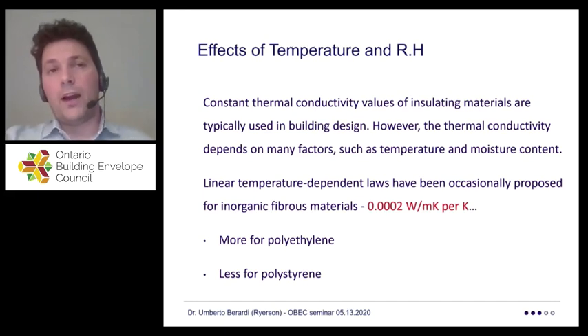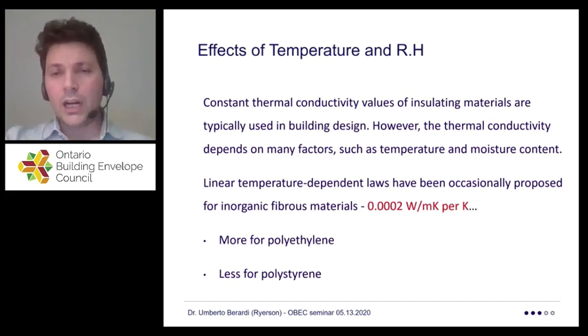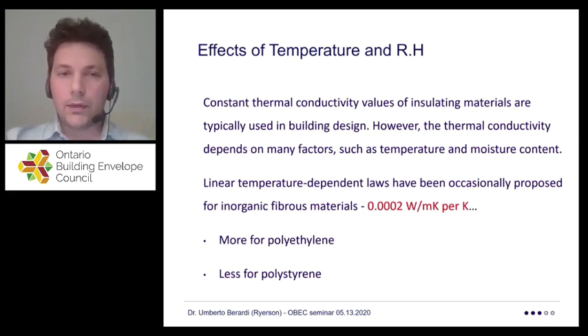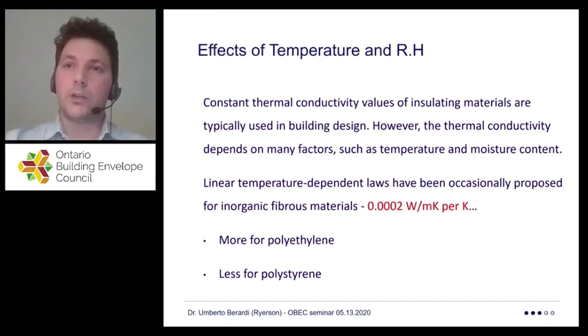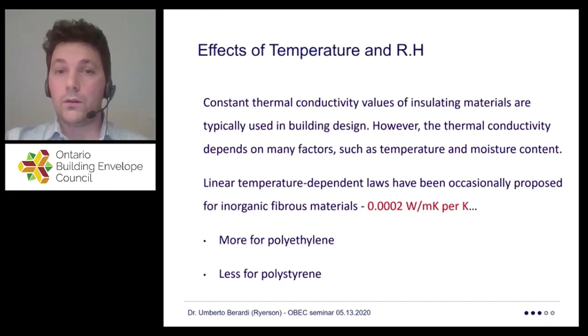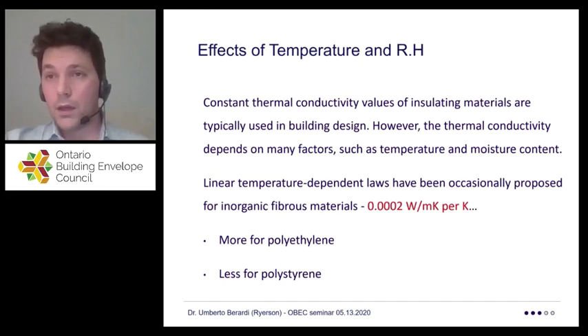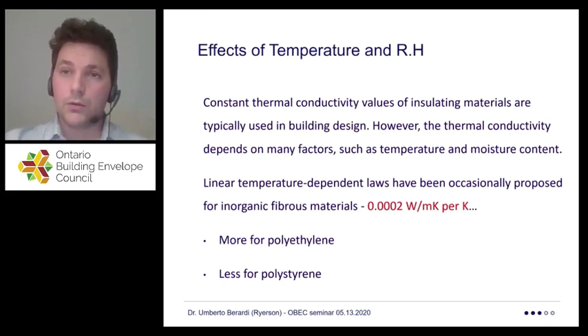So first of all, temperature effects on thermal conductivity. In general, although we typically use constant thermal conductivity, I'm safe to tell you today that every material will have at least a linear temperature-dependent law. The linear temperature-dependent law really is an effect of radiation. Higher temperature brings more radiation, which brings more thermal conductivity. So typically, a safe assumption could be to use a dependency in the range of 0.0002 watts per meter Kelvin per Kelvin. So this tells you that a material at high temperature will conduct more, and at low temperature will conduct less.